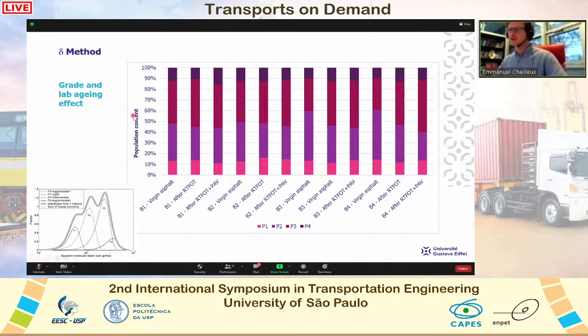If we look at the population content with aging and with the grade of bitumen, we recognize a typical result we also have with the SARA analysis, for example. What is important is the 2 intermediate populations. So during aging, but also during the changing of grade, there is an exchange between these 2 intermediate populations, while the lowest and the highest one remain relatively stable. So very interesting result, which confirms what we see with other techniques. So we are very confident with the delta method technique, and we think we can have very good information about the molecular structure variation with aging, and also with lots of other parameters.